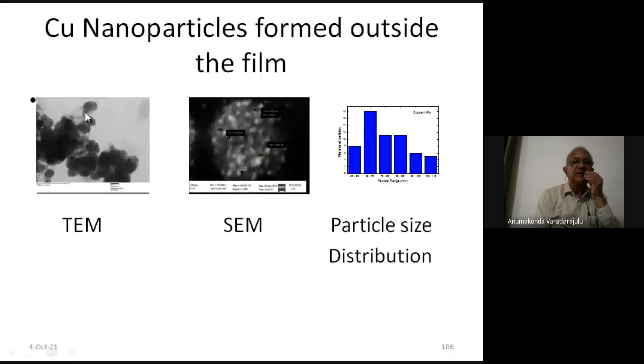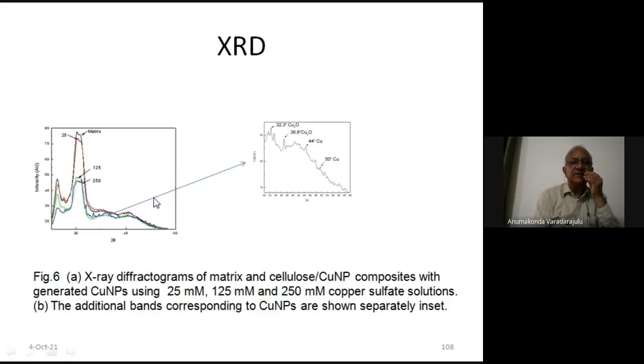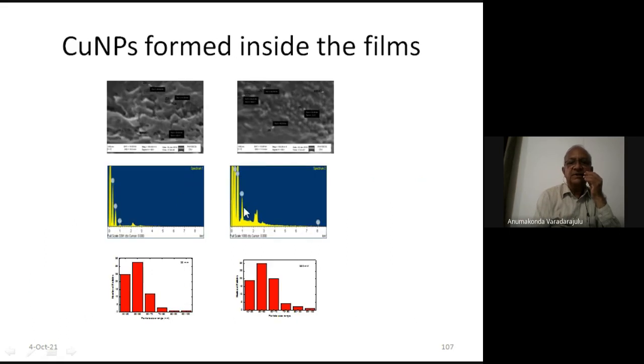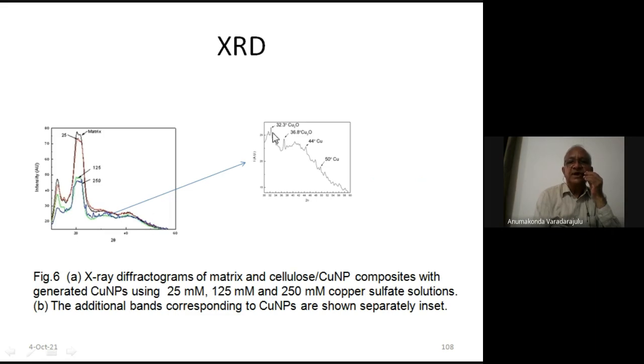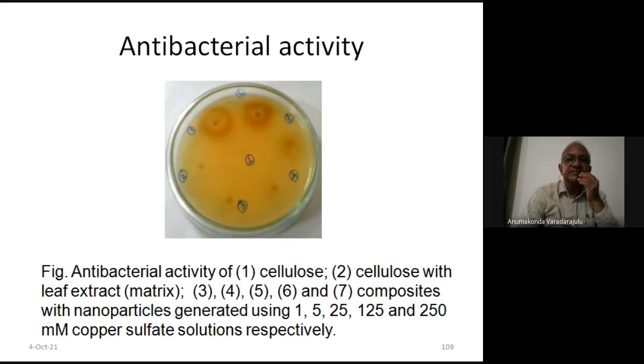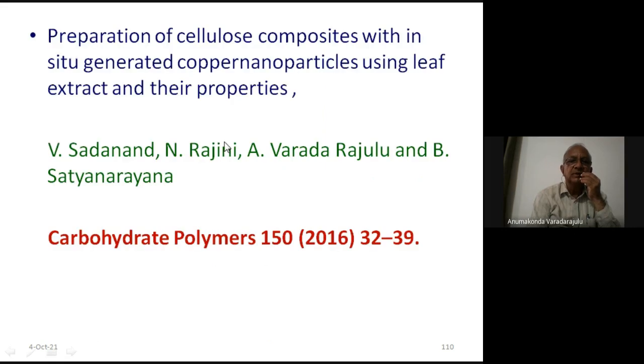So this is the TEM analysis, spherical nanoparticles, SEM analysis, spherical nanoparticles. And then this is the EDX spectrum showing the copper element here. And this is the particle size distribution. XRD also showed additional peaks corresponding to both copper and copper oxide nanoparticles. So both copper and copper oxide are there in nano form, with the size range between 60 and 90 nanometers. They showed very good antibacterial activity with clear zones around this film. This we published in 2016 itself. You can find this in the Carbohydrate Polymers journal.